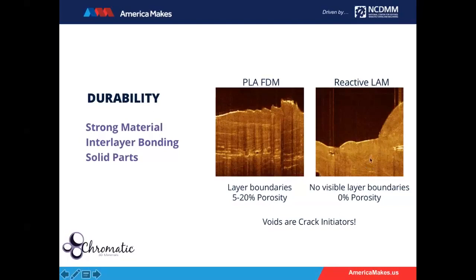And the reason why this is important when it comes to durability is that voids, and those small voids that we leave behind if the materials don't form a solid part, are actually crack initiators. And so with FDM, even with the most durable resin, if we are leaving voids behind, if we have that porosity, we're making a part that is going to have a greater tendency to form cracks and be less durable. So what we're able to achieve with our printing technology is not only start with a strong material, but we get excellent interlayer bonding and we form 100% solid parts.